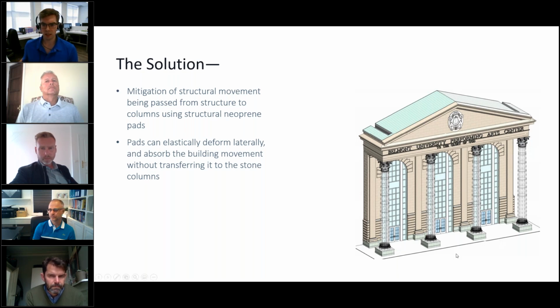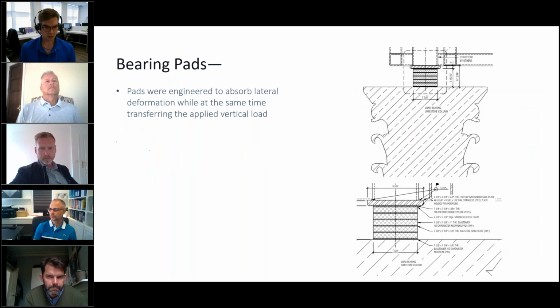The solution that we settled on in this case was to use a system of neoprene pads that could elastically deform laterally and absorb the building movement without transferring large lateral forces down to the stone. This slide coming up shows a detail of how the bearing was provided with the neoprene pad connecting the steel structure to the stone. And you can identify another consideration that needs to be made when integrating structural systems, that being the requirement of providing adequate bearing for the steel structure on the stone, because especially with softer stones such as limestone, a steel member that bears on a fairly small point could easily crush the stone if it's not properly engineered so as to adequately distribute that force.